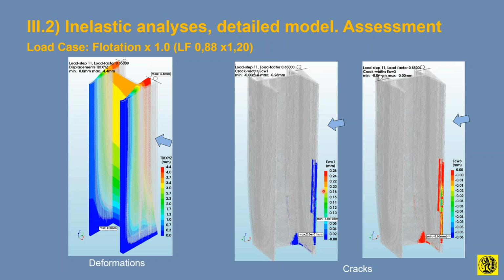And then the crack widths in this case, we do have 0.2 millimeters in this area. In the fixity, the principal crack is actually at the bottom of the continuity to the remaining caisson here. So already the longitudinal walls start cracking. So really, what caused cracking was the cantilever deformation of this internal partition. Already cracks develop at the lower third of the external wall, which is 45 plus the cross-section thickness here. And then we have cracking in the 3 directions here.